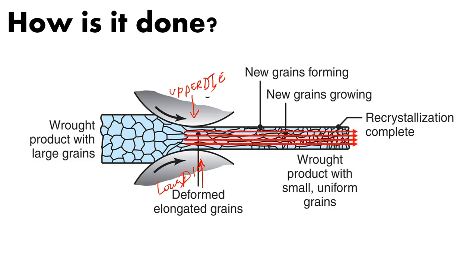You actually start to align your grains. You get an aligned grain flow. So this is a really important part of the process actually becoming a stronger metal. You're actually changing the structure and the mechanical property of the metal at this point because of that new grain flow that you're giving it. And all this together makes for a much stronger, much more ductile, much less likely to fatigue piece of steel or whatever metal you're forging than if you had just left it in the cast state.